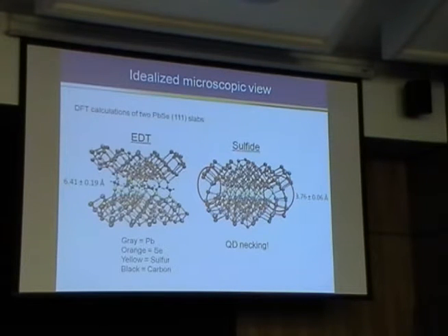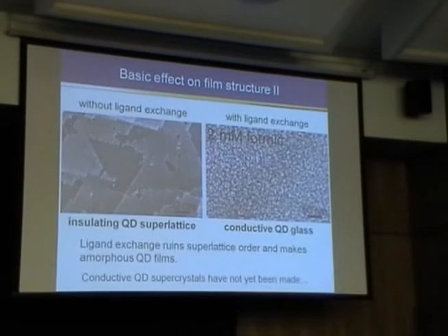And this is something that people are very worried about and interested in, using these very, very small ligands, that we may actually be doing things like necking particles together, causing some very limited fusion of the quantum dots, which will improve charge transport to some degree, but it also will increase the disorder within the material. And we'll talk about that in detail tomorrow. So this is a hint, perhaps, that we're seeing quantum dot necking in our simulations.